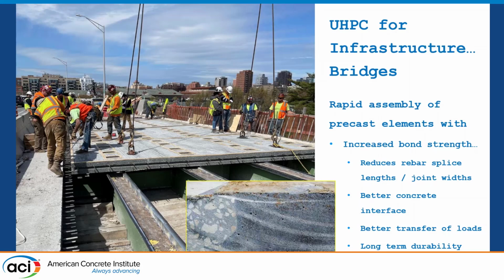This is traditional concrete. This is from a precast beam. This is the UHPC that's in the joint. Because the bond strengths are so very good, we're able to reduce the splice lengths on our steel. So instead of having a 25 or 30-inch joint, now I've closed my joint width down to maybe 6 or 8 inches. And I'm no longer the weak link in between my precast bridge elements. I'm now the strongest part. So I'm able to transfer the loads in between the different sections of the bridge, and I'm able to do that very completely with great long-term durability.